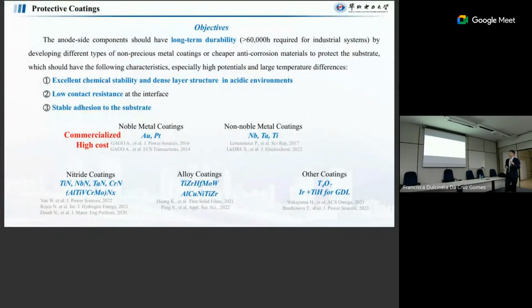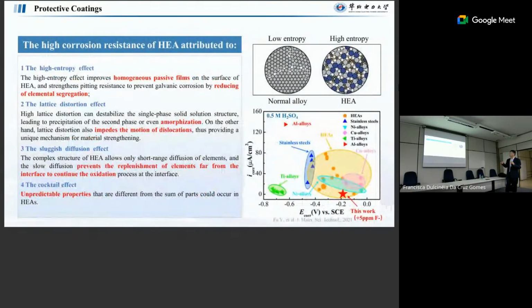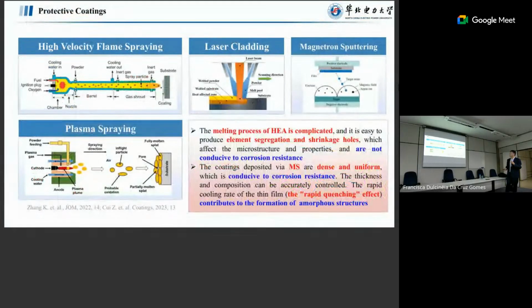Then the last is about the coating. Coatings also, we try to replace the gold and the platinum with niobium, titanium, and titanium nitride. Yeah, this I will go fast. The first we developed is this HEA system, a high entropy alloy system. Yeah, in our work, for the potential, we can get a good range at low current density. Yeah, here we use the technique magnetron sputtering.